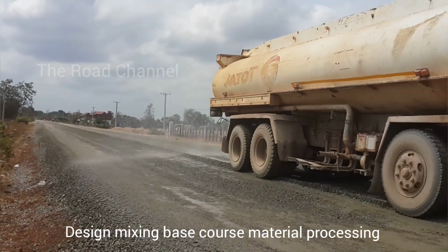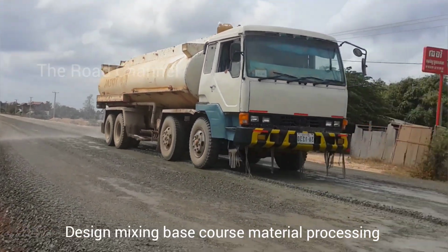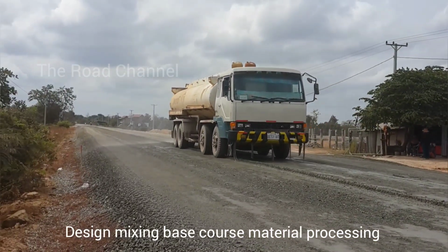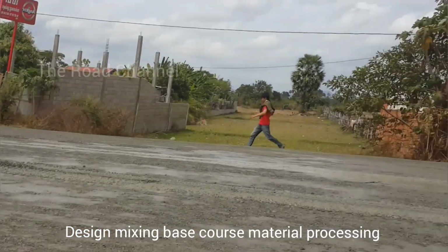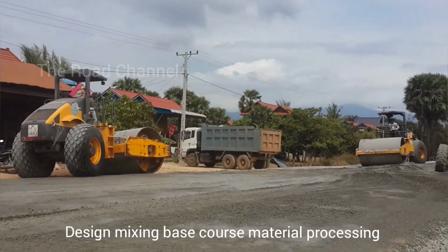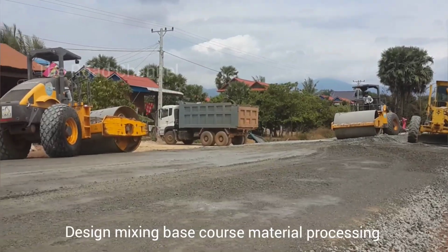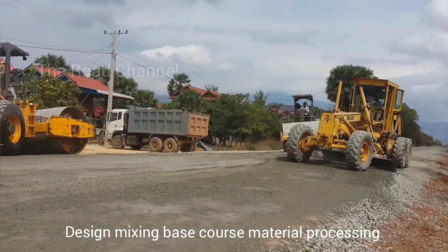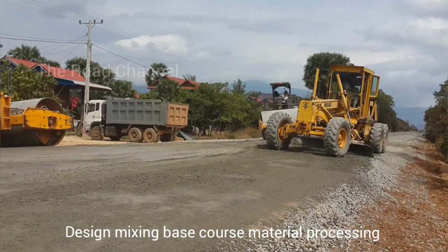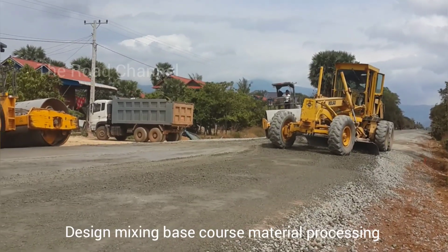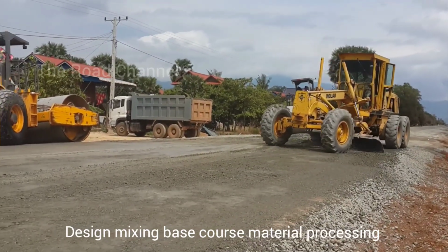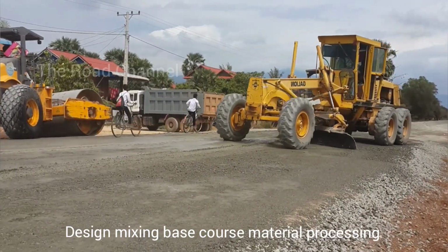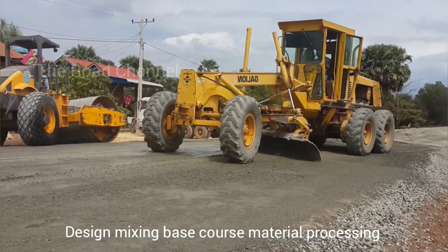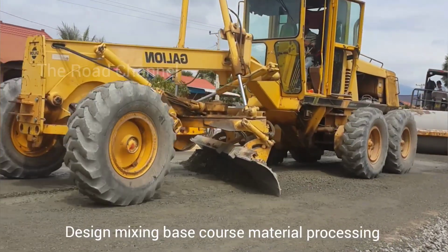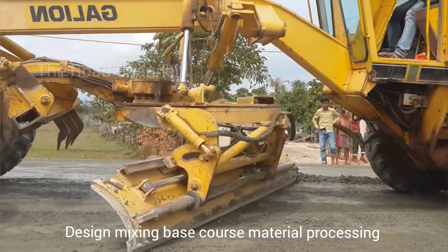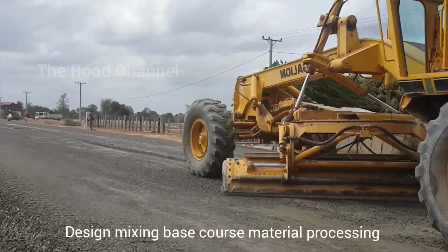5. Mix design adjustments. Moisture control: based on the Proctor compaction test, determine the required moisture content. Usually, water is added during construction to reach optimal compaction. Proportioning materials: if your initial material does not meet gradation requirements, adjust by mixing additional coarse or fine aggregates to meet the target gradation curve. Additives: if needed, additives such as lime, cement, or fly ash can be introduced to stabilize the base course, especially in cases of weak materials.